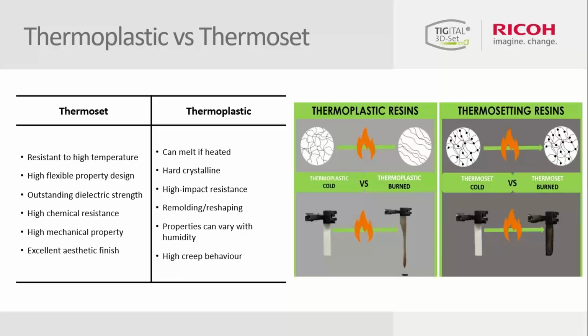If you look at thermoplastic materials, most are crystalline systems. That means during printing and cool down, you have a huge shrinkage. For PA12, we are at nearly 4%, which means shrinkage and warpage of the materials. Our Thermoset materials have a shrinkage below 1% during the printing process. This is one of the big advantages of Thermoset materials, because it enables you to print huge parts. Just one example: plates of 20 by 20 centimeters, 10 centimeters high.